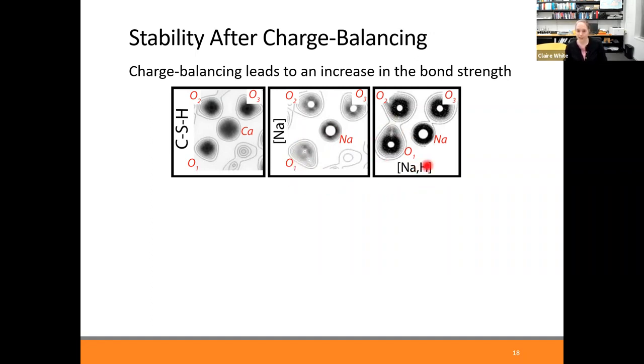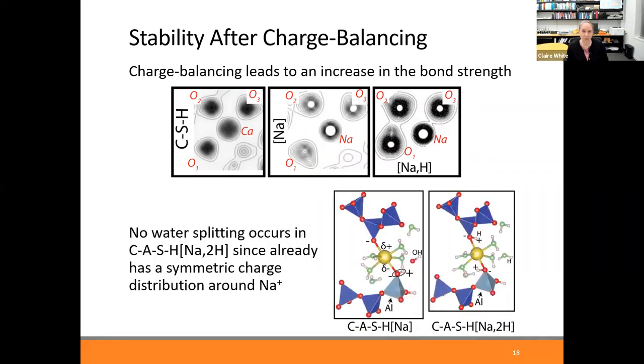However, when there's a hydrogen in the system as well, you can see that the bonding strength has increased. So this is one of the ways that we've been able to get a sense of what impact hydrogen is having on the system through this charge balancing mechanism. We also saw what happened in this system without the hydrogen. If you've got a sodium in the system and you've also got aluminium in the bridging site, you don't have a symmetric charge distribution around the sodium. However, when you have charge balance in this structure, we do end up with a nice symmetric charge distribution around the sodium, which seems to enhance the stability of the structure.